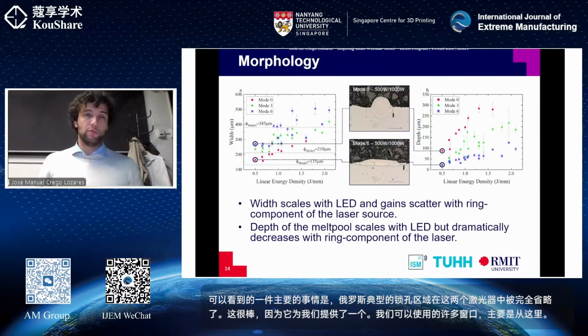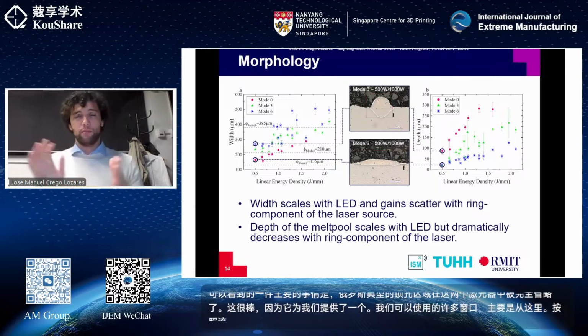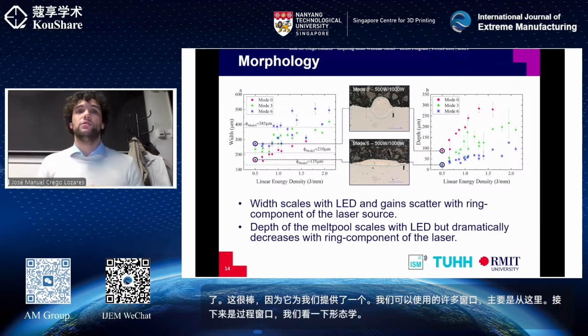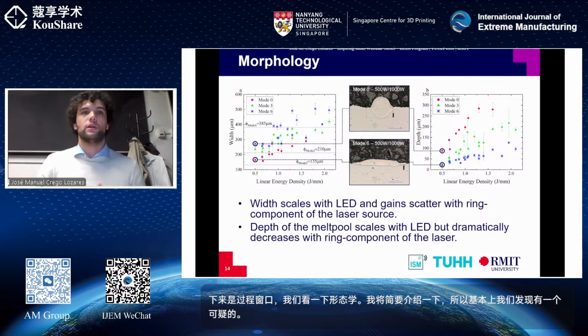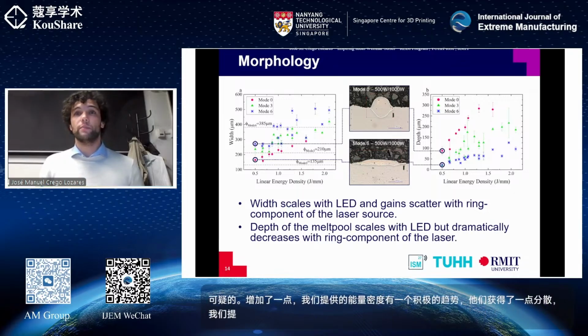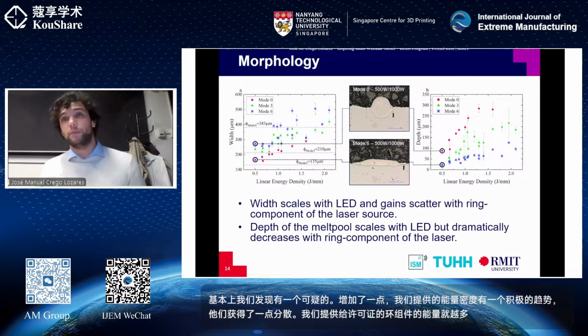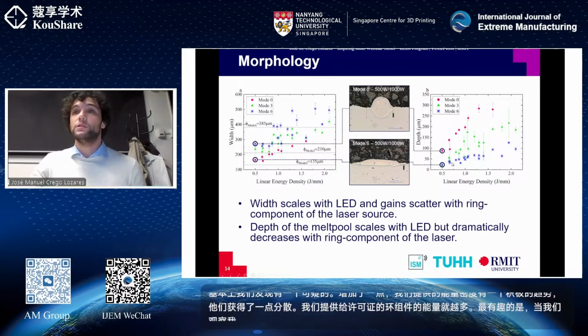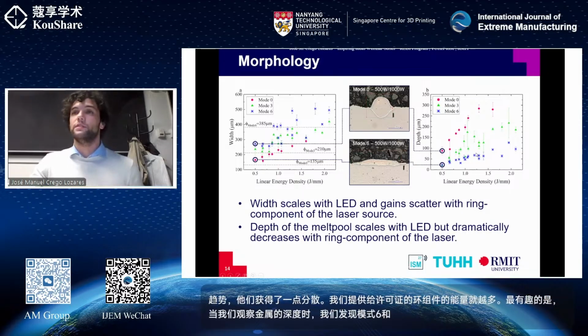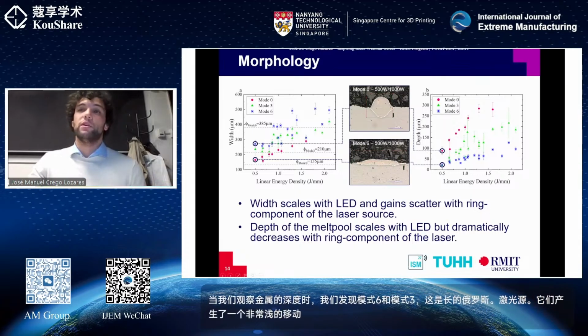Following the processing windows, we look at the morphology, which I will briefly go over. So basically, we found out that the width, as expected, increased a little bit, had a positive trend with the energy density that we supplied, and gained a little bit of scatter the more energy that we supplied to the ring component of the laser. Most interestingly, when we look at the depth of our melt pool, we found out that mode 6 and mode 3, which are the non-Gaussian laser sources, produce a very shallow melt pool, which was extremely interesting compared to the Gaussian, which grows very fast in depth.